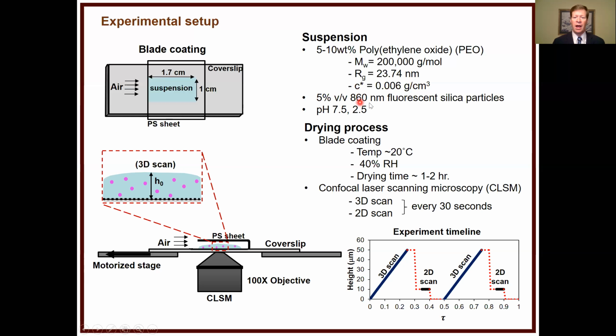And then we're going to also add roughly micron scale silica particles that are fluorescent. So that allows us to image. And then we're going to change the pH to change the interactions between those silica particles. And so the drying process now, again, that's just blade coating first, and then we're going to let it dry. All these samples dry in roughly an hour, but we're going to just rescale that time.